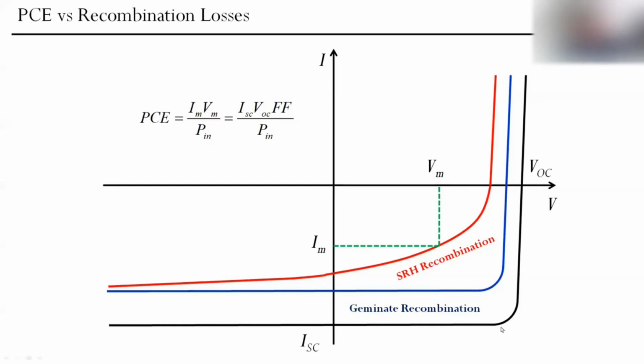So if we have no geminate recombination and trap-assisted recombination, we have a solar cell very close to ideal. We have high VOC, open circuit voltage, high short circuit current, a high fill factor. You see that here is the maximum. We don't lose much because our maximum power point current and voltage will be very close to short circuit current and VOC. And PCE, power conversion efficiency, is determined by the product of these three parameters. So all of them are large and performance is high.